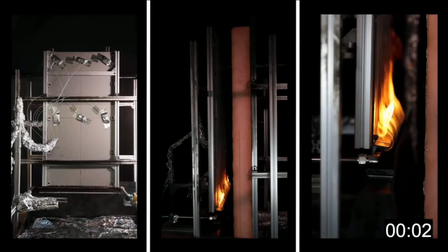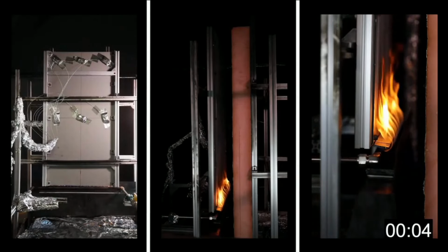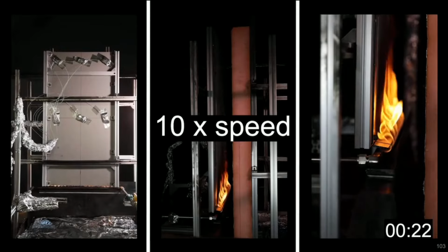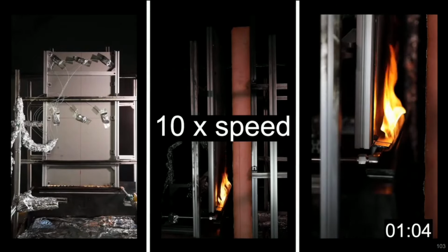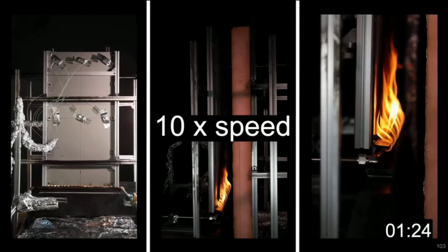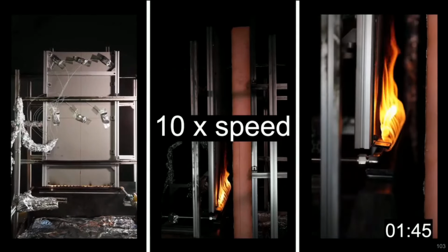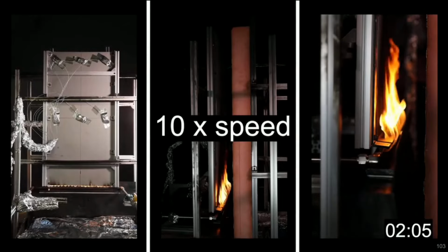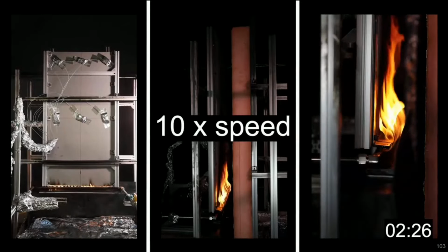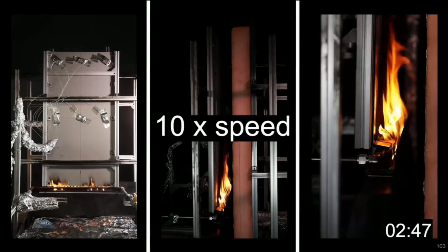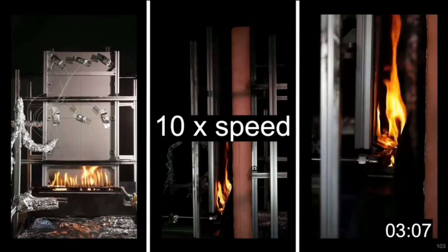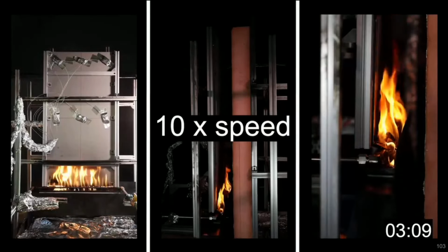You can see that when the burner is moved into the joint, the flame is drawn into the cavity and begins to interact with the ACM. Again, I'm showing this at 10 times speed. It takes around 1 minute and 30 seconds of heating before the polyethylene starts to drip out of the ACM and into the tray below. You can view that particularly in the leftmost view here. For about 90 seconds, the rate of dripping increases.